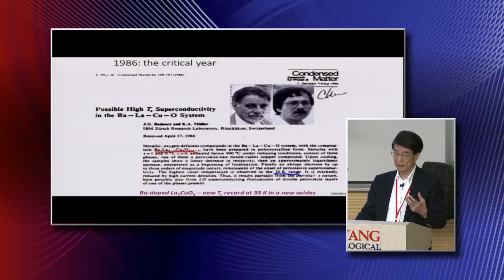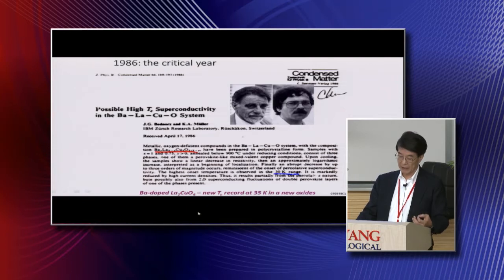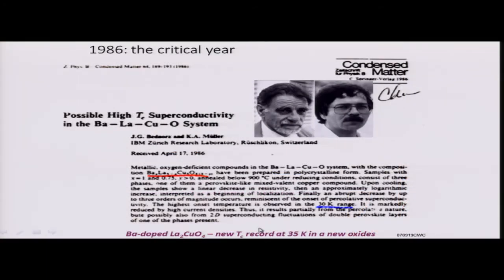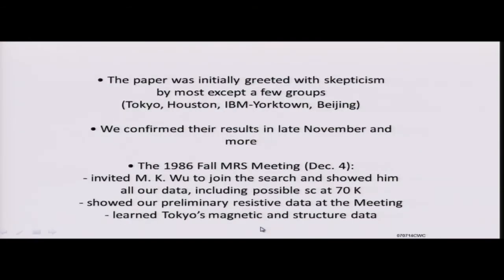But J.G. Bednorz and K.A. Müller published this paper saying possible high TC superconductivity in the barium lanthanum copper oxide. This is a perovskite-like transition. Essentially, they dope the lanthanum, so-called 214 compounds, but they use a different composition and then get a record TC of 35 degrees Kelvin. And the paper initially was greeted with skepticism by most except a few groups, because usually superconductivity was supposed to happen in metals, and the oxide is supposed to be insulating, not even metallic, let alone superconductivity with high TC.